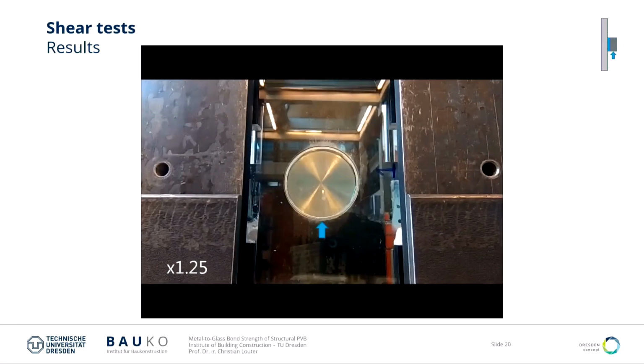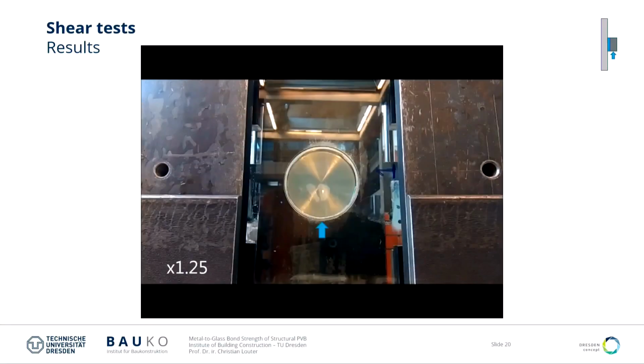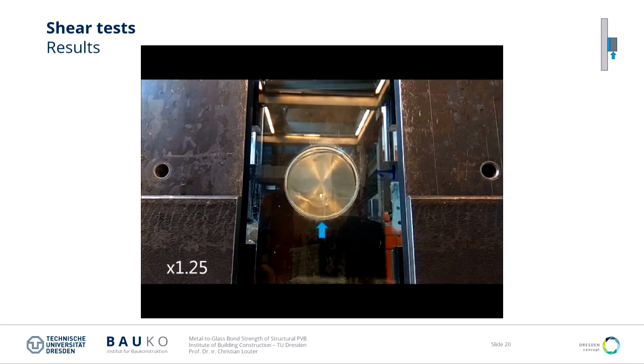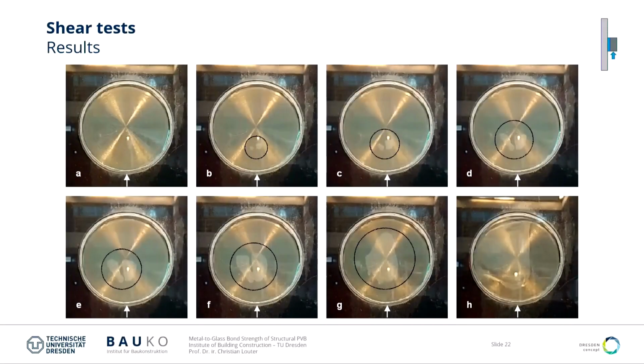This is a video. In the beginning, you don't see that much happening. This is just to indicate that the force is moving upwards. You can see delamination starts there, and it's progressing upwards a little bit. Until we reach failure of the specimen, then you have complete delamination there. Here you can see it again, but in pictures. So it starts from this point, and then it's progressing in this manner until we have full delamination there.